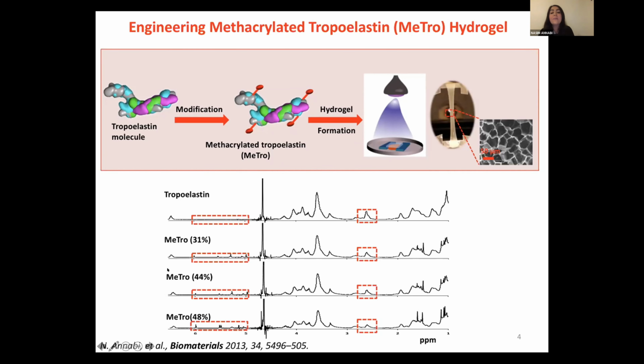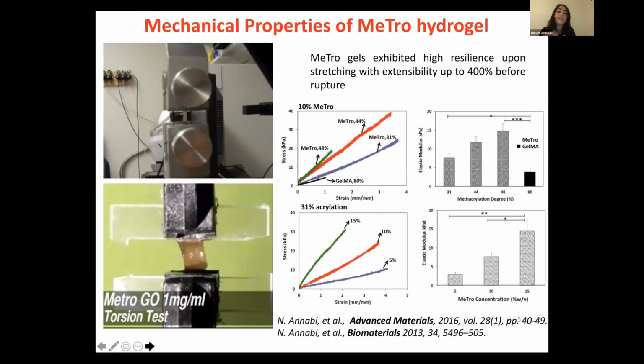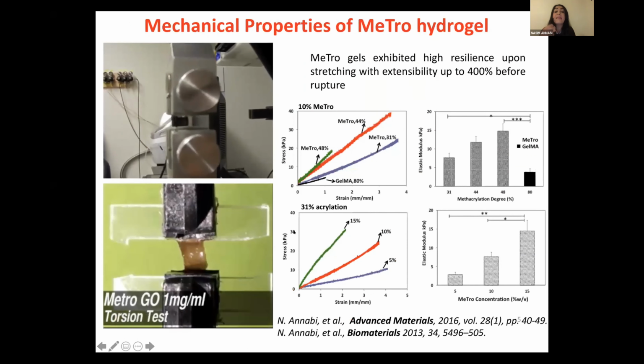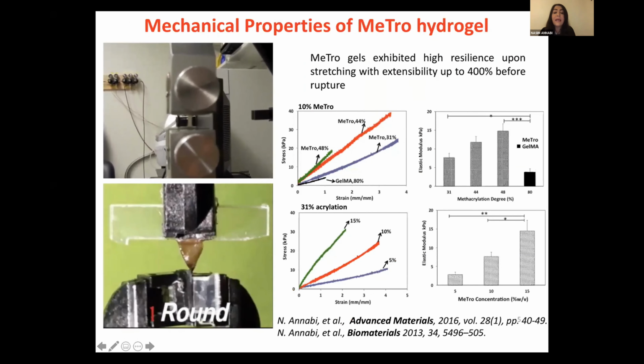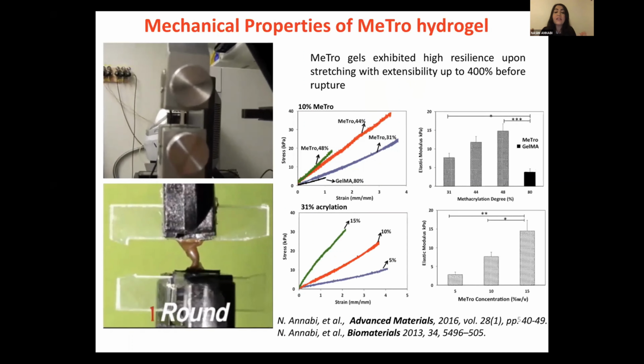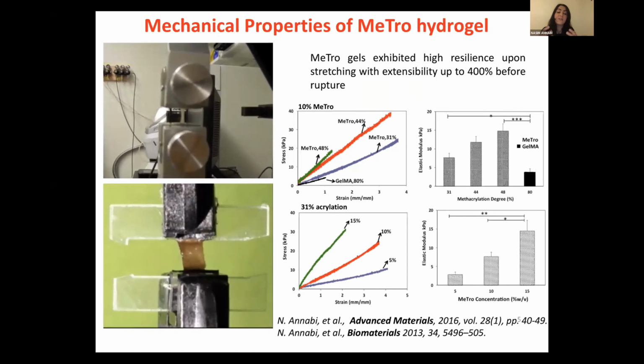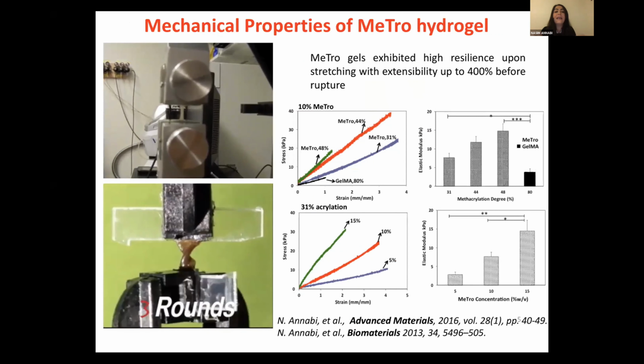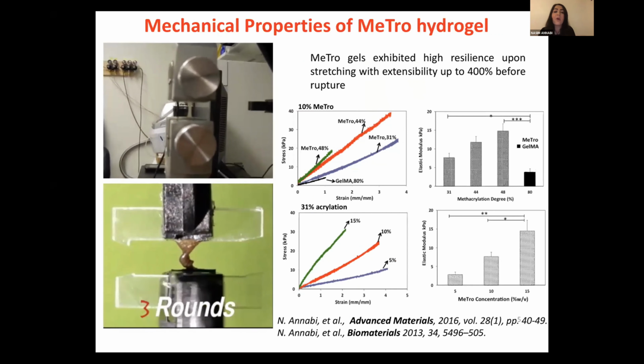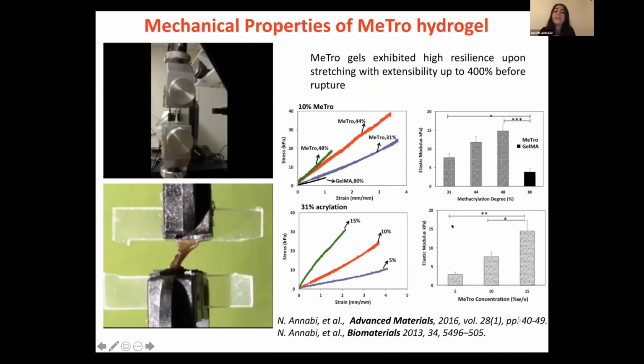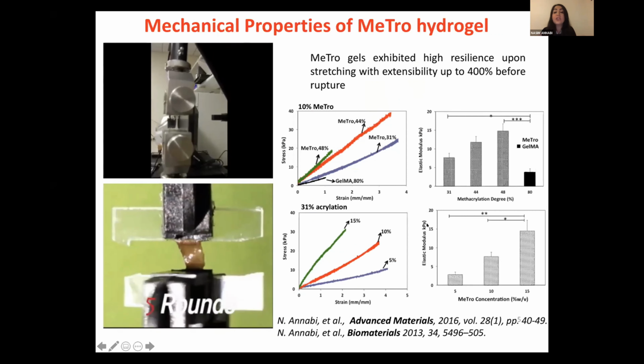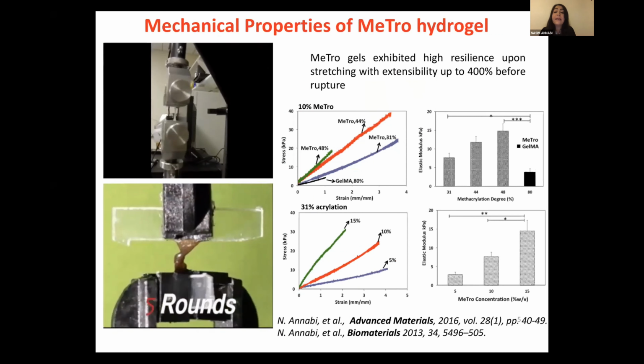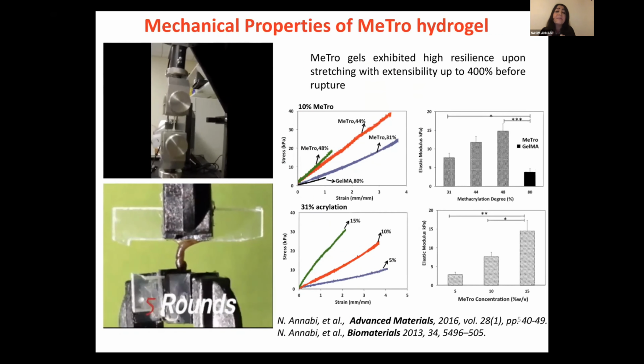And we show that by changing the degree of functionalization in MeTro, you are able to tune different properties of this biopolymer. And one important property for tissue engineering applications, as you know, is the mechanical properties of the material. If you work with naturally derived materials, although they have lots of great advantages, they lack elasticity and proper mechanical properties. With MeTro, by this modification, we show that the hydrogels are highly elastic and they can stretch up to 400% before we rupture them.